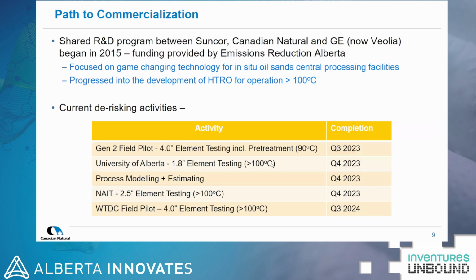We have testing ongoing at the University of Alberta. Currently testing 1.8-inch diameter elements above 100 C using synthetic water. We have process modeling and estimating going on, and that's important to establish those benefits I talked about earlier. And when we do some testing and we get data, we feed it into our modeling to refine the model and refine our business case. Very shortly, we're going to move to 2.5-inch element testing at NAIT at temperatures above 100 C using both synthetic and produced water. And then next year, we've got our pilot at the WTDC that's 4-inch diameter elements at temperatures above 100 C.